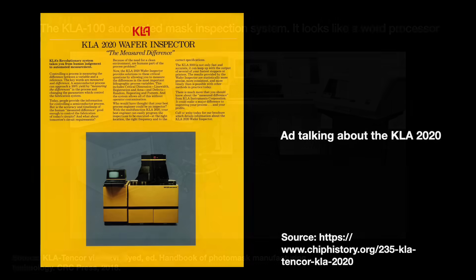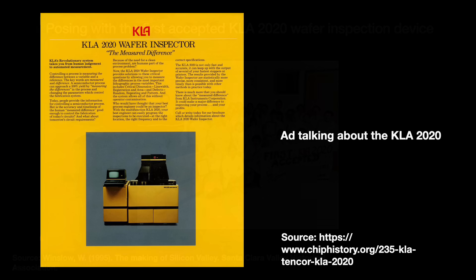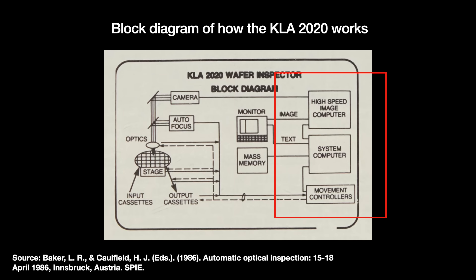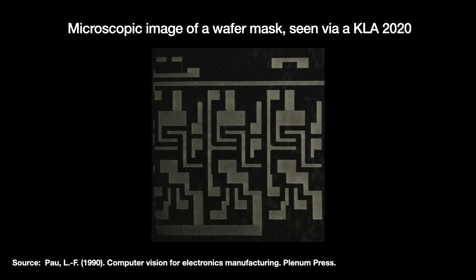In 1984, KLA released the KLA-2020 — the first automated pattern wafer inspection tool working right on the wafer production line, referred to as being inline. At its heart, the KLA-2020 is an automated, illuminated, high-speed camera with a microscope attached. The camera takes pictures of the wafer at varying magnifications defined by pixel sizes of 10 microns, 2 microns, etc. The computer then compares those images to that of a neighboring die to find defects, using image processing algorithms — the most common being a simple subtraction of one image from the other. The KLA-2020 is called a bright-field tool, where a light source illuminates the die to make its features easier to view.